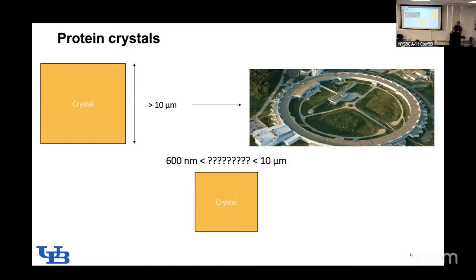If it's less than 600 nanometers and you have protein crystals, just blot that grid like a cryo-EM grid, put it in the TEM, and Merry Christmas. There's a really weird kind of inverse Goldilocks zone between 10 microns and 600 nanometers, where it's really of no use to send it to a synchrotron, unless in a few very specialized beamlines, and putting it on the TEM is a complete waste of time.